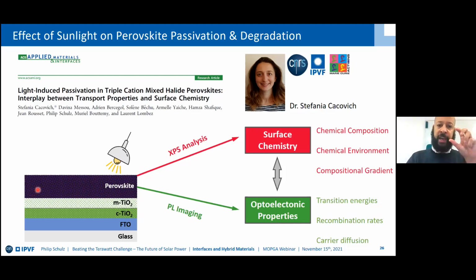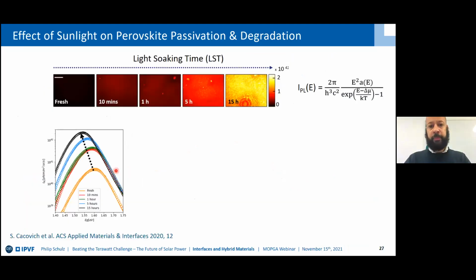The clue, however, is to couple XPS surface analysis with PL imaging, and therefore see how a change in the surface chemistry, for instance in the chemical composition and with compositional gradients and so on, impacts the optoelectronic properties: transition energies, does recombination of carriers change, and do this for a variation of aging conditions. And if you look at it, you first get these different PL images with different light soaking times. We begin with a fresh sample, and you see this brightening here, effectively an efficiency or intensity increase, setting in already after 10 minutes, but continuing up to 15 hours.